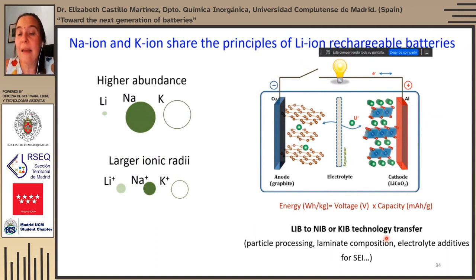And indeed, many of the processing parameters, like particle processing, how to make secondary particles, the composition of the laminates, where besides the active material you have a conducting carbon and you have a binder, the additives that are used in the electrolyte for the formation of the solid electrolyte interface, many of these parameters can be transferred from the lithium ion battery to the sodium and potassium ion battery.